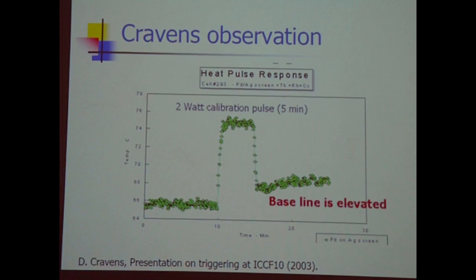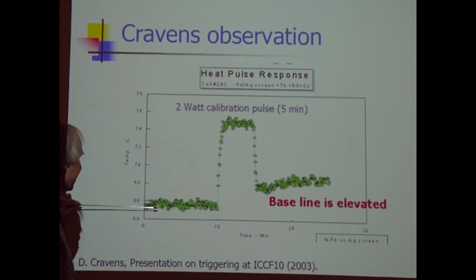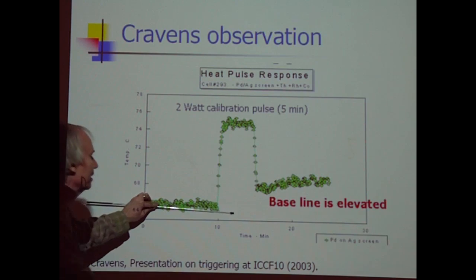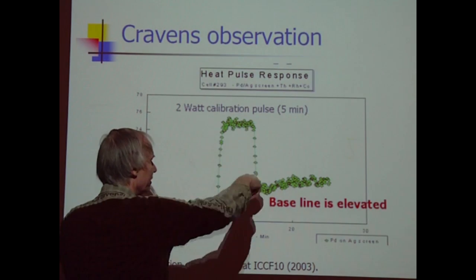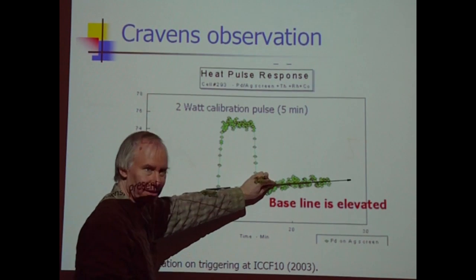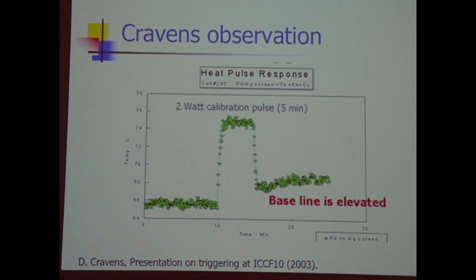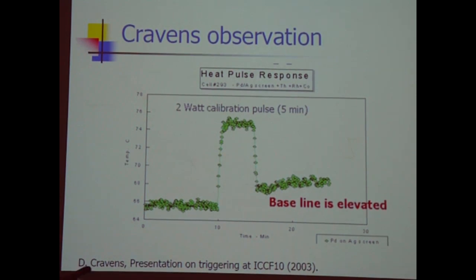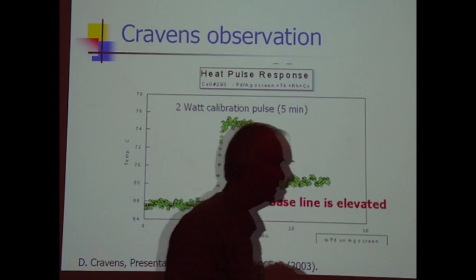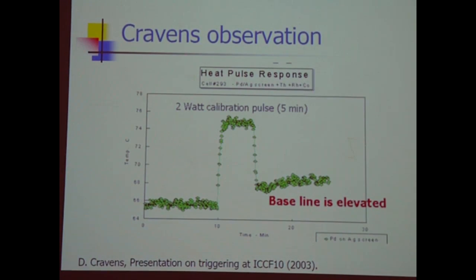Here's another observation of the effect. This is done by Dennis Cravens in a very different experiment. So here's his temperature baseline, calibration pulse, and then temperature following the calibration pulse. So the calibration pulse, by being present, has raised the amount of excess power being produced.